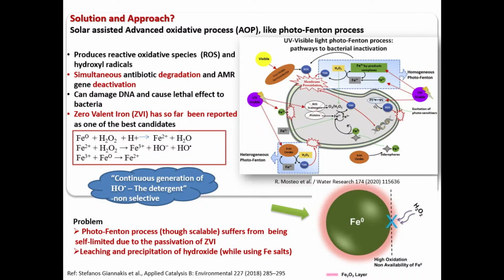But the disadvantage of the photo-Fenton process, though it's scalable: when you use ZVI, even though the initial efficiency is high, there is a passivation layer which kicks in after a certain time. So you need to take care of that. Also, there are other problems like leaching and precipitation of hydroxide, especially when you use iron salts. So what do you do?